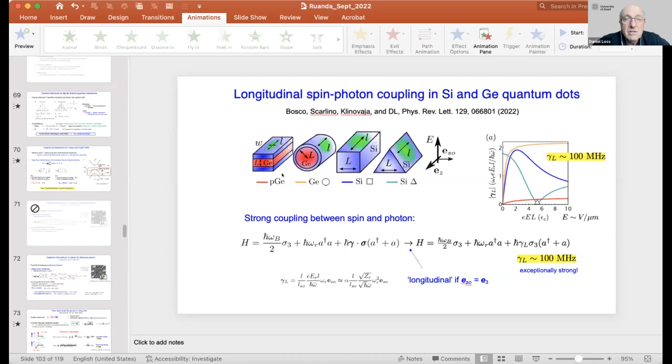If we look at the Dirac equation, then the momentum of the electron and its spin are coupled. And it's this type of spin-orbit interaction, the relativistic correction, which gets very, very much enhanced in a solid state environment through the lattice structure, because there are atomistic potentials very close to each other, and the electrons have to go through that. And there the effective spin-orbit interaction can be amplified by a factor of 1,000,000 or so, such that the tiny correction which comes from the relativistic spin-orbit interaction in free space has a very substantial contribution.